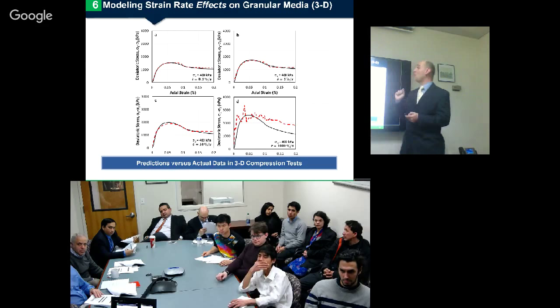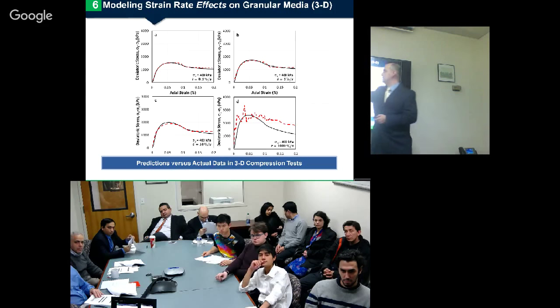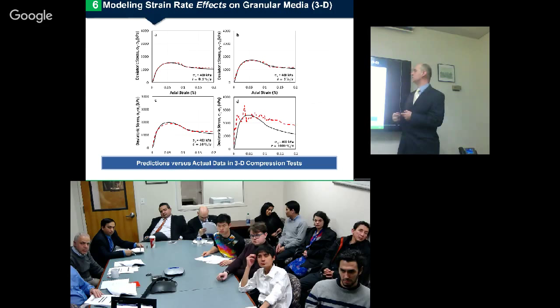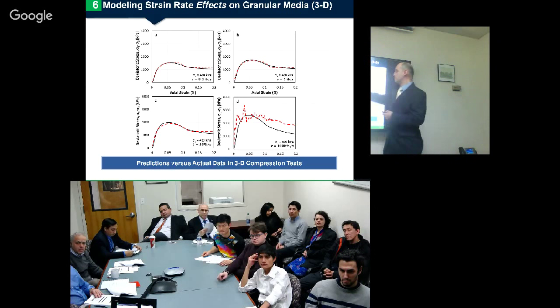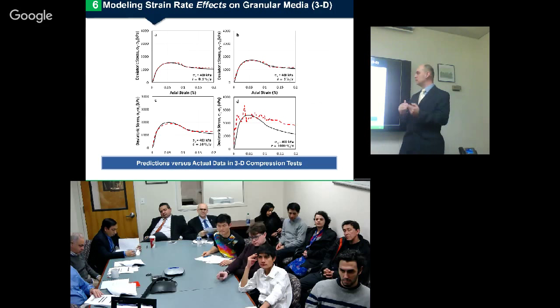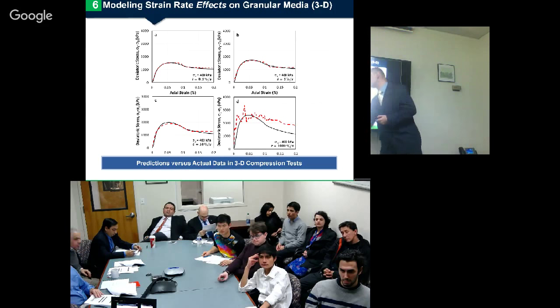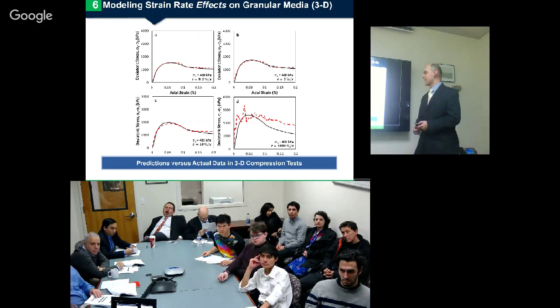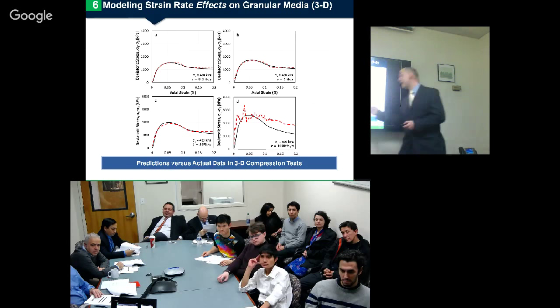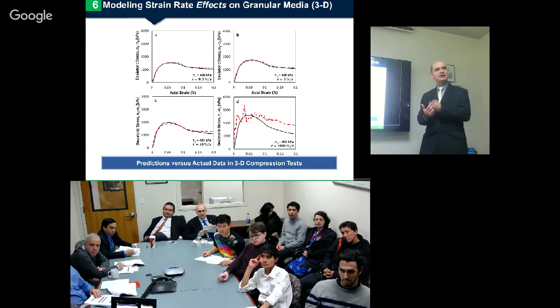Now for 400 kPa at 0.1% per second, we can see these 2 lines that are close to each other. For 400 at 1% per second, we also have a good match between those 2, and at 10% per second as well. I got this plot of 1000% per second based on results that came from the drop weight test.